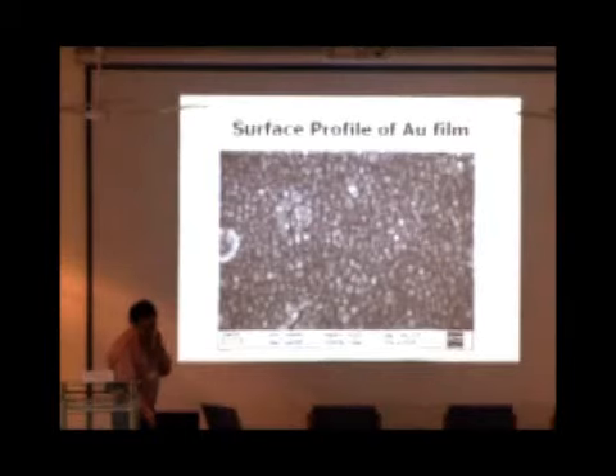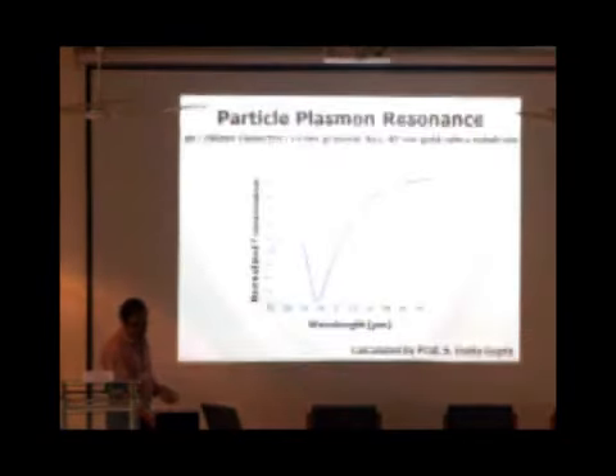We did lots of theoretical calculations to identify what these modes correspond to. This is an SEM image of the top layer showing the particulates, showing that we actually have localized plasmon excitation in these structures.